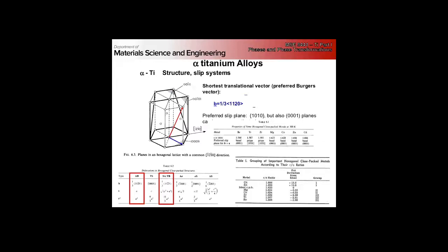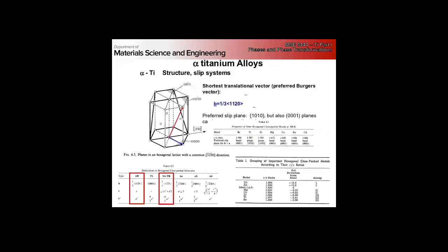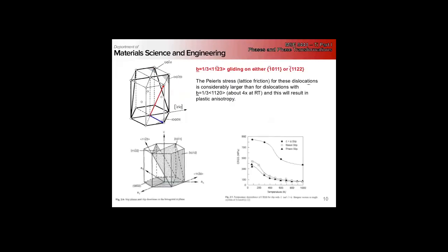And so we can look at different dislocations that we see in the system, and we can play with it geometrically, and basically see that we're going to prefer the prismatic system. It's going to give us the shortest dislocation, the shortest Burgers vector. So the critical resolved shear stress for prismatic is about a 1/4 of that for basal. I mean, not 1/4. Sorry.